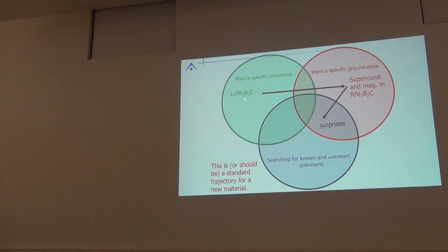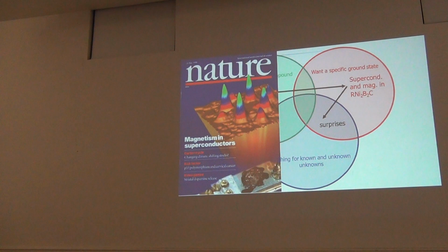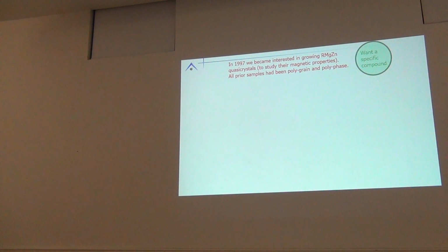This is sort of a standard evolution. We wanted a specific compound, but then quickly with the compound mastered, we wanted to study a specific ground state, superconductivity with magnetic interactions, and then often in basic research, there are surprises. In this case, the surprise was if you start looking at the small angle neutron scattering, which, as we mentioned yesterday, is a common way of imaging the vortex lattice. This was the first clean example of a hexagonal to square transition of the vortex lattice seen via neutron scattering. It was subsequently seen by some groups with tunneling microscopy, but these are not easy materials to cleave, and therefore you suffer a little. All right, let's look at another example.